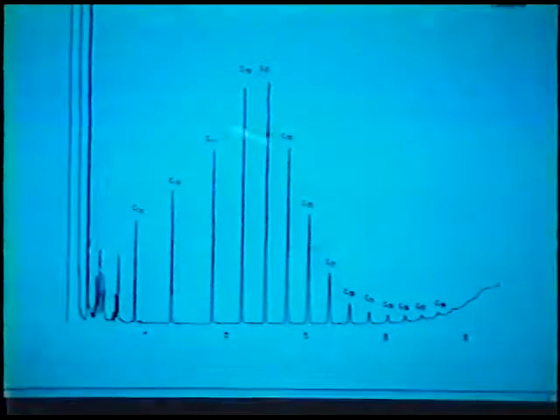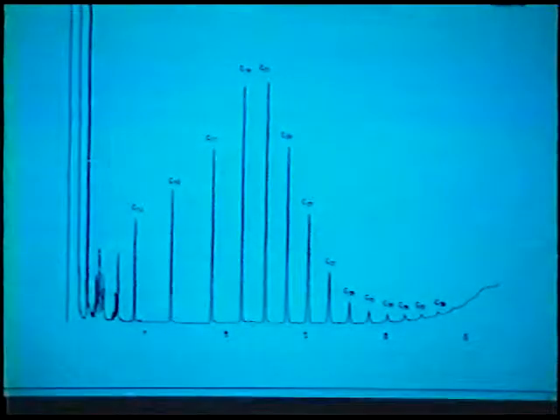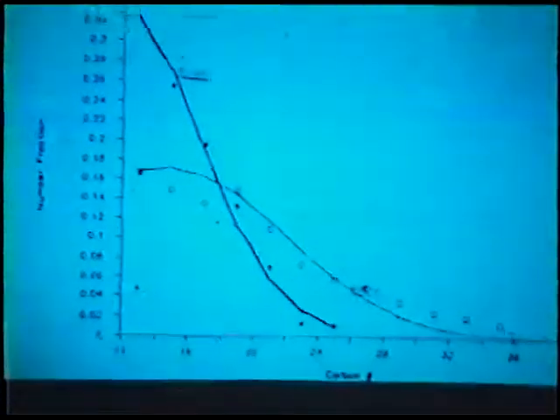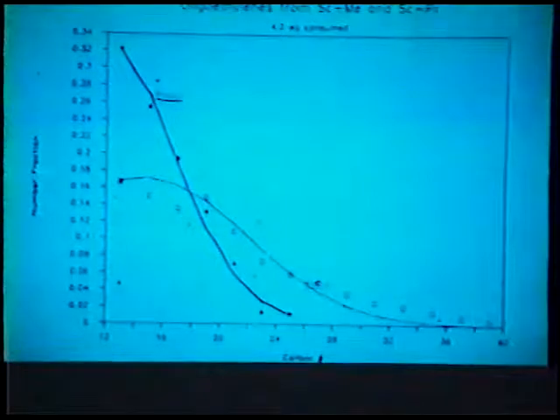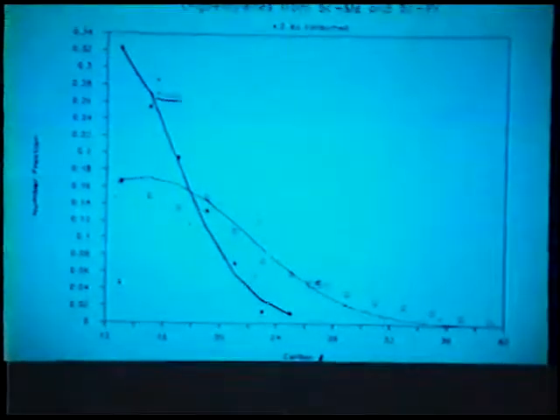One is we only get the odd carbon number alkanes, straight chain alkanes, again implying no chain transfer has occurred, because if we did beta hydrogen eliminate, the hydride ethylene insertion would start an even carbon chain oligoethylene process. And so no chain transfer appears to be occurring on that basis. Furthermore, you can fit the molecular weight distribution. Here we have 4.2 equivalents consumed, but you can see you can satisfactorily fit it to a simple Poisson distribution, assuming that you have a living system, and importantly, all the scandium centers are active.